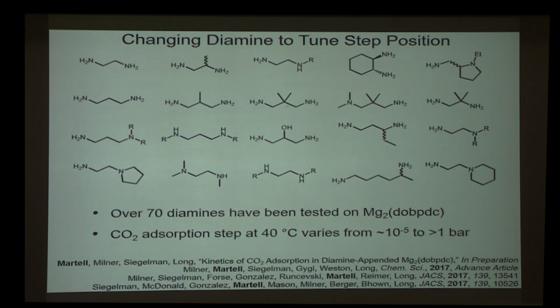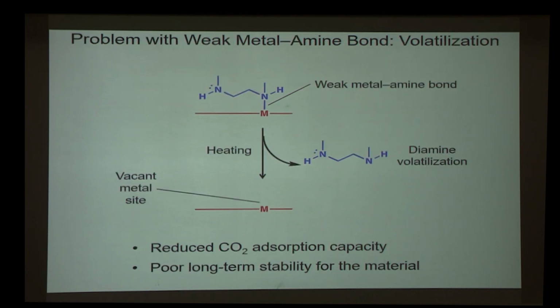And following these basic strategies, we have now tested over 70 diamines in the context of this framework. This is work done in collaboration with Rebecca Siegelman and Phil Milner, colleagues in the Long Group. And we found that we were successful in tuning the adsorption step over nearly 5 orders of magnitude. So we did indeed come up with a class of materials that was highly tunable in terms of the adsorption properties. I mentioned that one thing we did to alter the thermodynamics was to weaken the metal-amine bond.